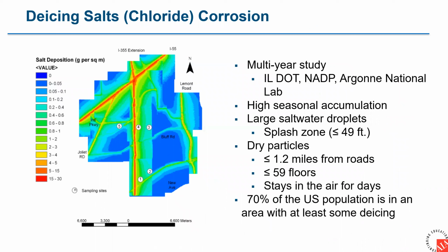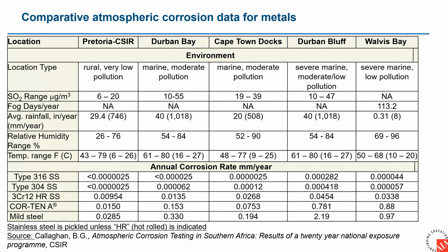The other primary source of salts is de-icing. 70% of the US population is in an area with at least some de-icing. A study in Illinois found that de-icing salts traveled at least 1.2 miles from roads and were found in Chicago up to the 59th floor. I have documented de-icing salts 2 miles downwind from a highway. So they have to be considered as well. Any source of salt must be considered.